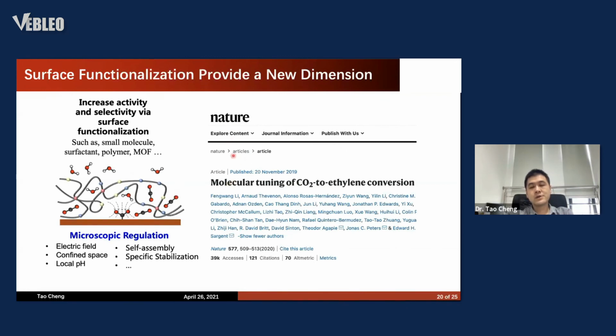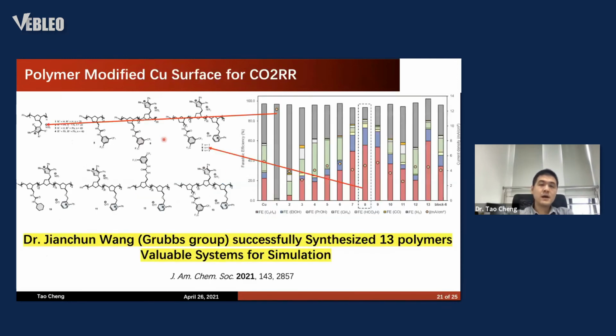There was one paper published last year showing that if you have a small polymer on this copper surface, it can significantly increase the performance. We are very lucky to have an experimental collaborator from Grubbs' group at Caltech, and Dr. Jianchun synthesized 13 polymers by finely tuning the functional groups. This is really systematic. If you compare the performance, you can see that it is actually very different. Please note that the metal is the same. All the metal is copper. The only difference is the polymer.